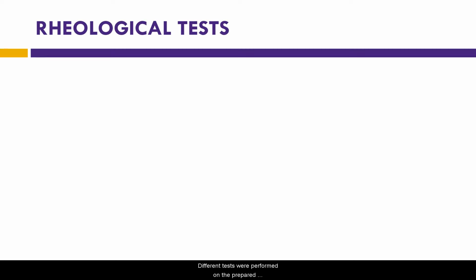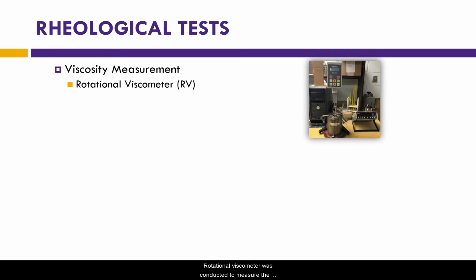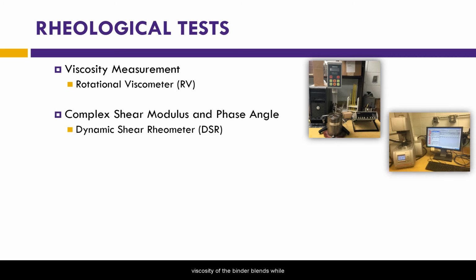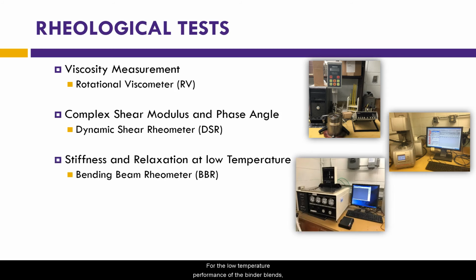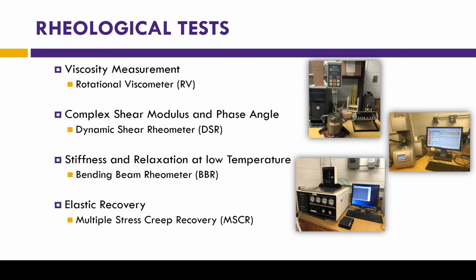Different tests were performed on the prepared binder blends with or without self-healing polymer and recycled materials to evaluate rheological properties of the prepared binder blends. Rotational viscometer was conducted to measure the viscosity of the binder blends, while dynamic shear rheometer was used to measure the complex shear modulus and phase angle of different binder blend samples. For the low temperature performance of the binder blends, bending beam rheometer was used to measure stiffness and relaxation at low temperature. Finally, multiple stress creep recovery test was conducted to evaluate elastic recovery of different binder blends.